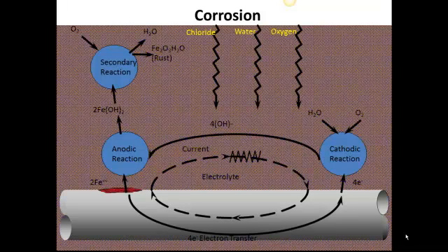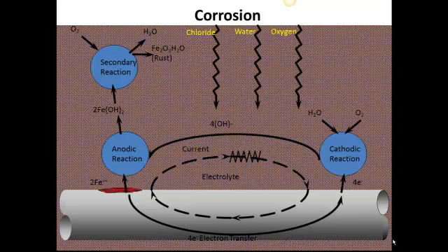When corrosion begins, you will find that an anodic and a cathodic site form on the surface of the reinforcing. This is because corrosion is an electrochemical process and causes a current to flow through the reinforcing, represented by the electron passage shown on the lower half of the screen. At the cathodic site, interacting with water and oxygen, this produces hydroxide ions. These ions complete the circuit and move to the anodic site, where they combine with the iron ion Fe++ to create iron oxide and other corrosion products. These products are expansive, so you see the indicative spalling, cracking, and delamination when corrosion progresses enough.